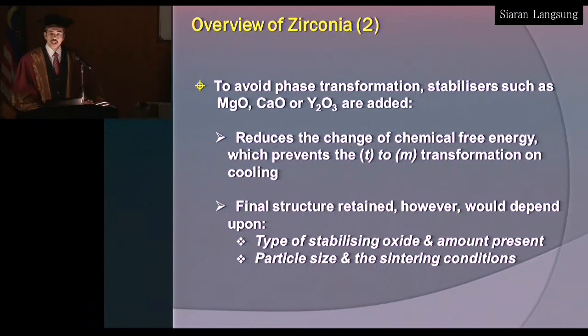Now, in order to overcome this problem, the interest in zirconia for engineering application lies in the solid structure form. So it's either in the tetragonal structure or it should be in the cubic form. Now, in order to stabilize the tetragonal structure or the cubic structure to room temperature, it is important to stabilize the zirconia material. Now, various stabilizers have been considered, such as magnesium oxide, calcium oxide, and yttrium oxide.